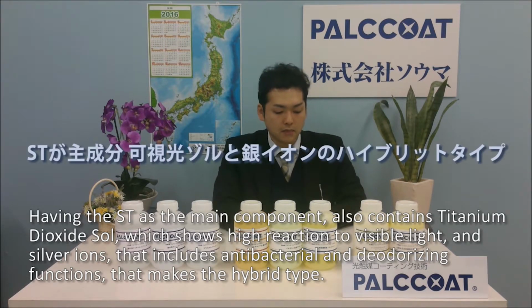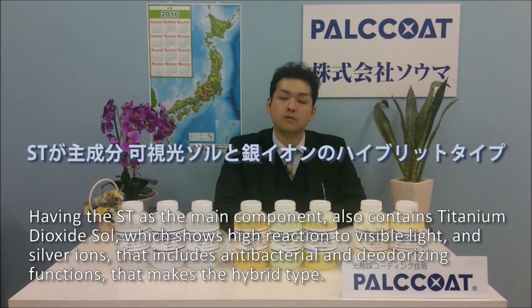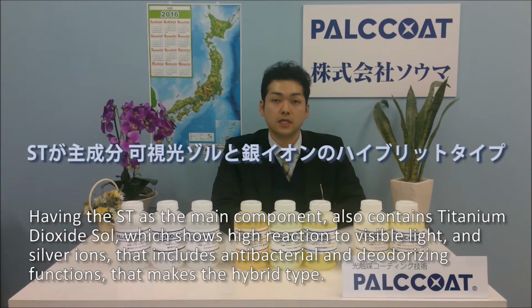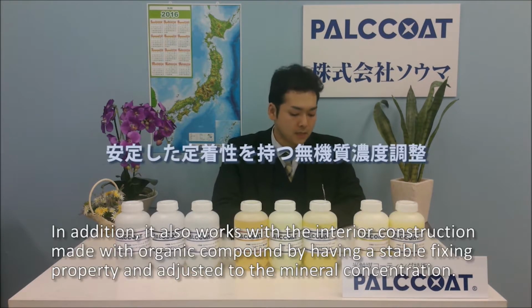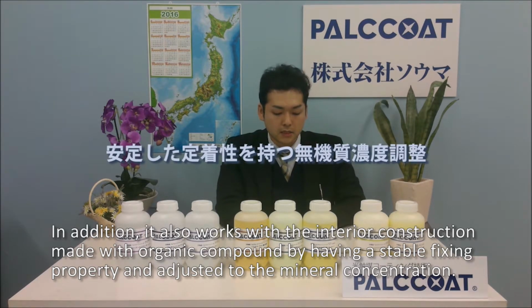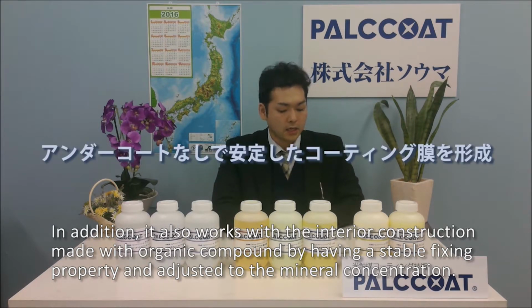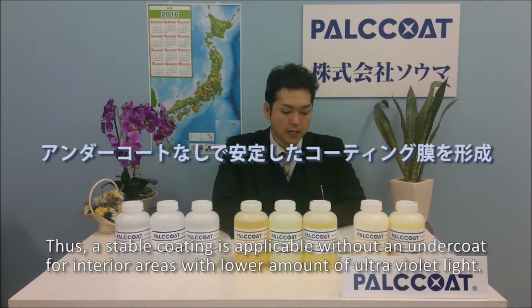Having the ST as a main component, it also contains titanium dioxide sol, which shows high reaction to visible light, and silver ions that include antibacterial and deodorizing function that makes this hybrid type. In addition, it also works with interior construction made with organic compound by having stable fixing property and adjusted to mineral concentration. Thus, a stable coating is applicable without an undercoat for interior areas with lower amount of ultraviolet light.